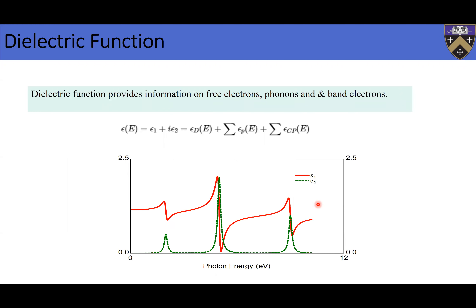Let's quickly go over the main thrust of the concept of the dielectric function. Remember, this is not the static dielectric function — this is the dielectric function as a function of energy or frequency, and it's a complex number with a real part and imaginary part. All of the behavior of electrons and phonons, whether free electrons or band electrons, are stamped on the dielectric function. So if you measure the dielectric function, you can get insights into the behavior of electrons, phonons, and the main constituents of the material you're exploring.